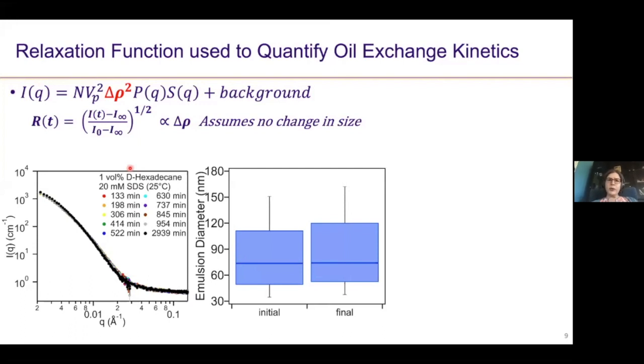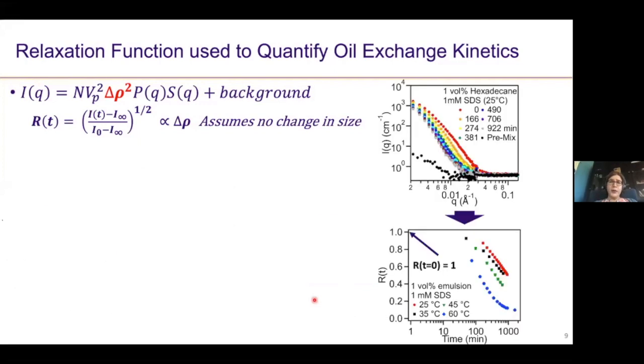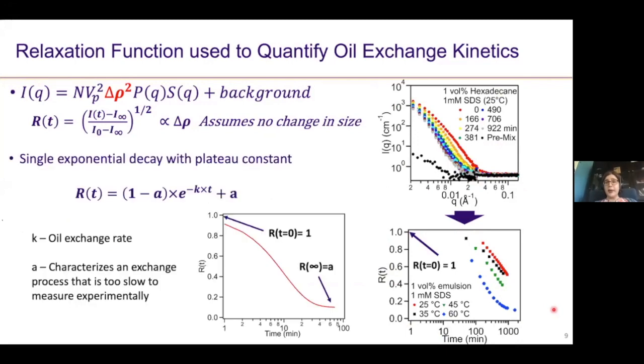And we can monitor the size change as a function of time. And we see that the size change is actually fairly small with respect to time. So what that allows us to do is then to apply this equation. So we can go from a plot of intensity versus wave vector to now a plot of this relaxation function as a function of time. And this gives us these new plots that we can then interpret by fitting them to some relaxation function.